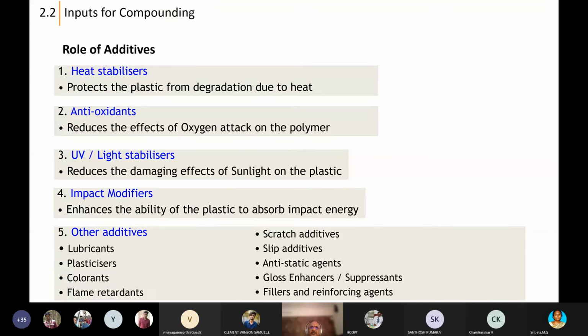Normally, when you measure the surface resistivity, you will get a value of 10 to the power of 14. Okay, the volume resistivity will be a little higher. When you add this anti-static agent, it will drop to a level of 10 to the power of 8. And when it drops further, to something like 10 to the power of 4, then you call it a conductive plastic. A good example is carbon.